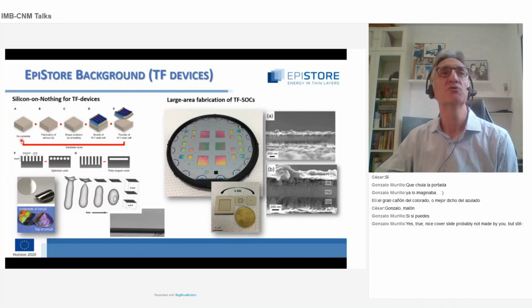And in order to produce this silicon-on-nothing, to produce this air gap below the silicon surface, we need to pattern the silicon with holes with a certain diameter, pitch, and depth, and then expose the sample to high-temperature annealing, and then the silicon evolves just by surface tension.